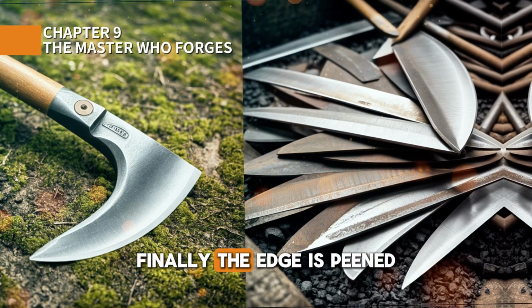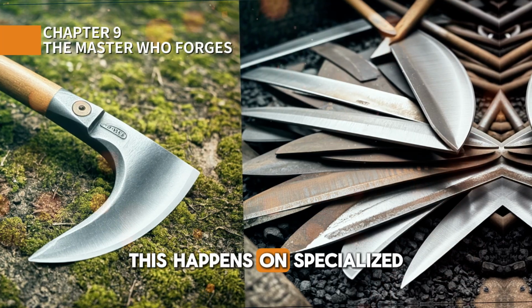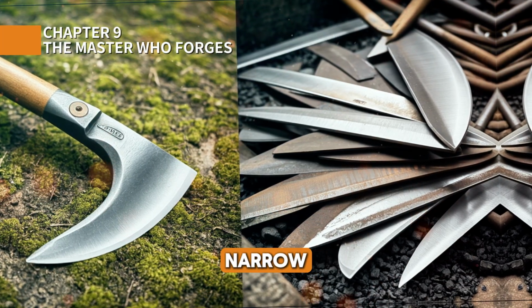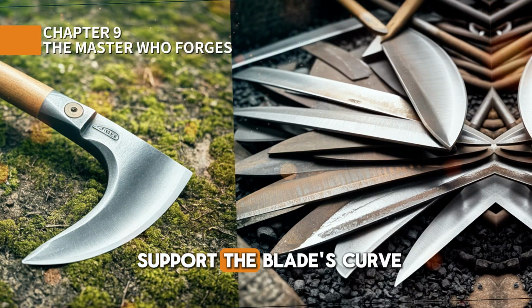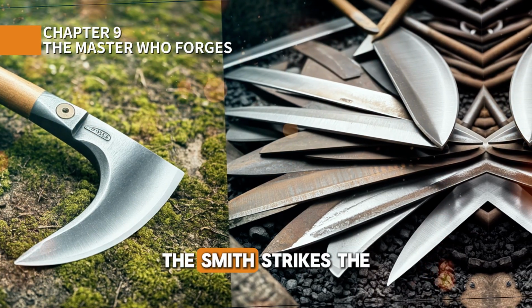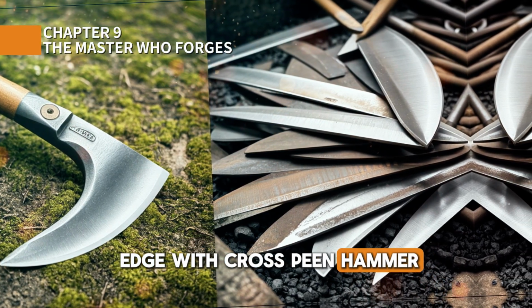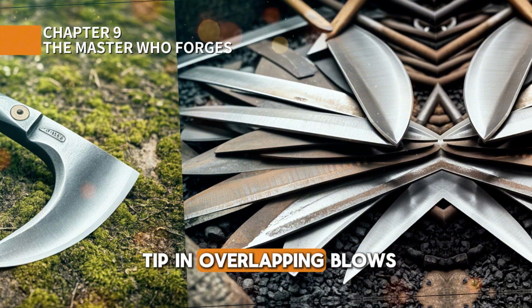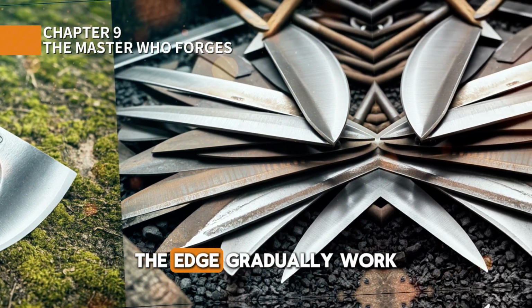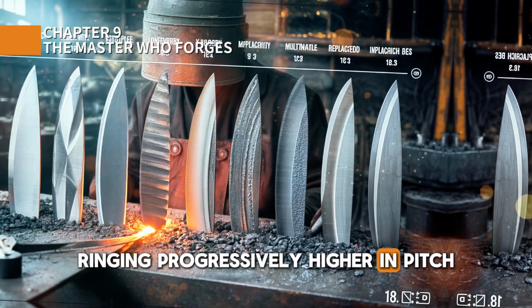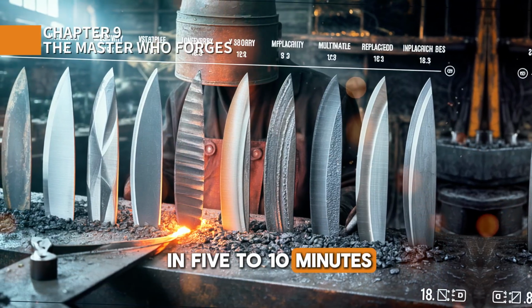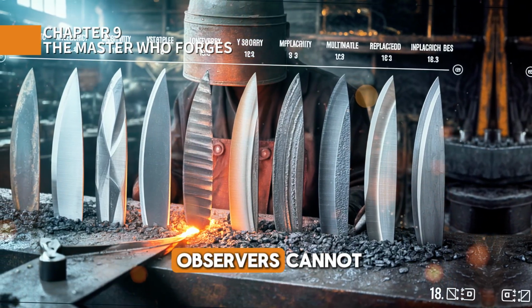Finally, the edge is peened. This happens on specialized peening anvils, narrow, hardened steel forms that support the blade's curve. The smith strikes the edge with a cross-peen hammer, working from heel to tip in overlapping blows. The edge gradually work-hardens, the steel ringing progressively higher in pitch. Experienced smiths complete this process in 5 to 10 minutes, producing edges that casual observers cannot distinguish but users immediately